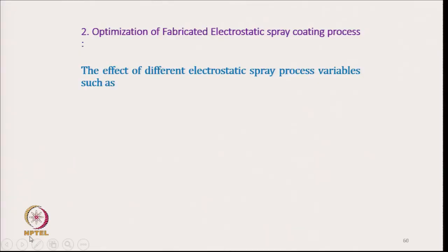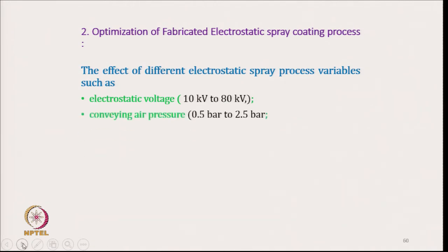The process parameters are the electrostatic voltage, this we can vary. Here the electrostatic voltage is varied from 10 kilovolt to 80 kilovolt. Then we can vary the conveying air pressure. In our study it has the range from 0.5 bar to 2.5 bar. Other variable is tow velocity.